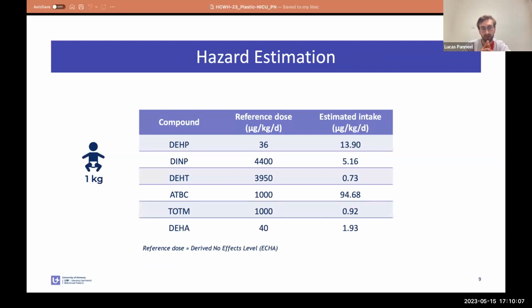And then we can compare the estimated daily intakes on the right column with the reference doses or the tolerable daily intakes or derived no effect levels. And then we can see that for all phthalates and alternative plasticizers we detected in our studies, the estimated daily intakes are below the reference doses or the derived no effect levels. Even for ATBC, for which we have estimated daily intakes of almost 100 microgram per kilogram per day, this is lower than the current reference doses that are there.